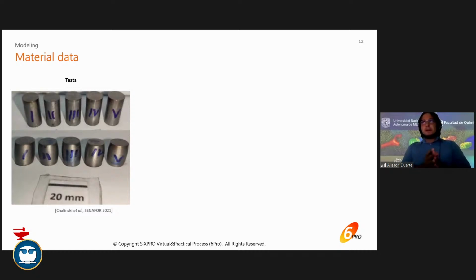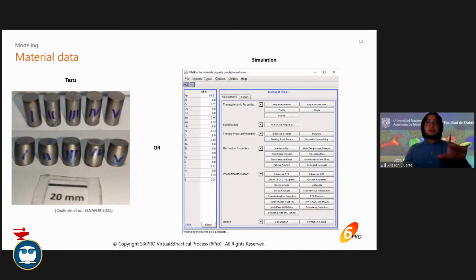For forging, the most common way is to get, for example, compression tests. In compression tests, you can see here 5 specimens, and they were all compressed. And from those, we get the material data. That's one possibility. Another possibility is to use software that already simulates the behavior of the material that we need. For example, this is JMatPro.